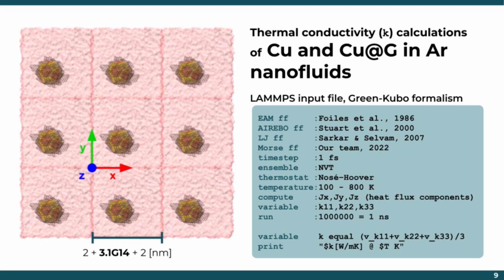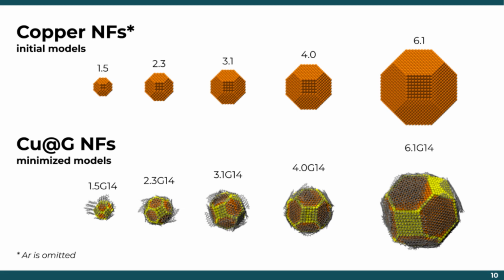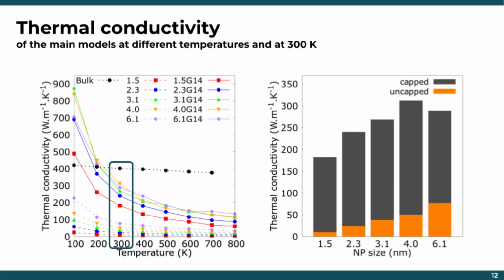The results indicate that copper capped by graphene nanoparticles are stable in an argon environment, and their structures remain similar at all temperatures. The copper capped by graphene nanofluids have an improved thermal conductivity compared to the copper nanofluids, being up to 20 times higher for the nanoparticle of 1.5 nanometers and up to 4 times for that of 6.1 nanometers.